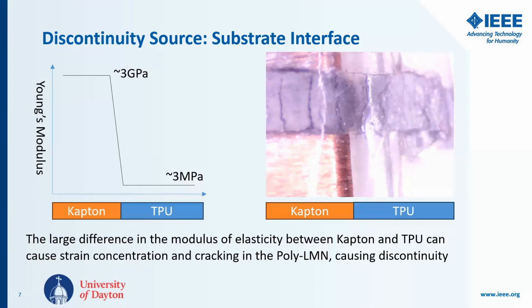The fact that you're going 3 orders of magnitude of the modulus of elasticity within a small area means that you can basically change the amount of stretch that an ink is going through under a very small amount of area. And this causes, in extreme cases, fracturing and cracking of our polyLMN liquid metal network. When the liquid metal network cracks, it causes discontinuity and failure of the sample.